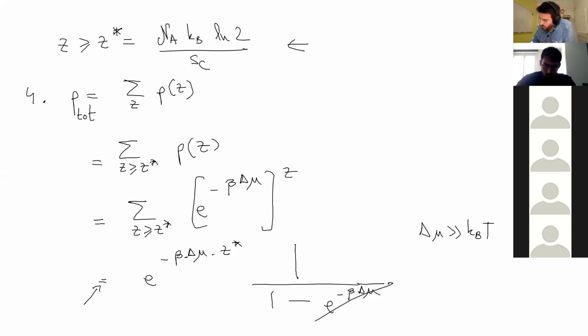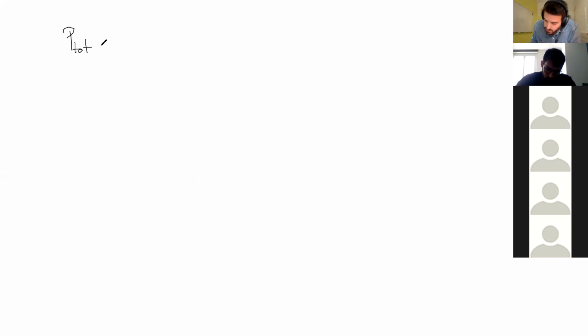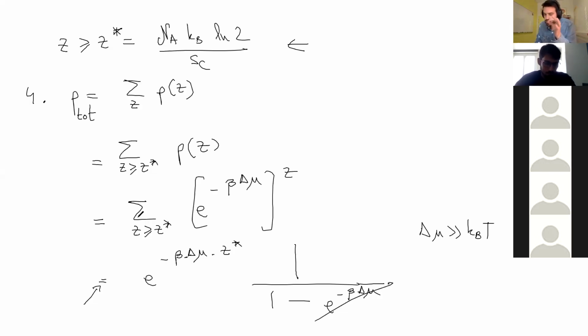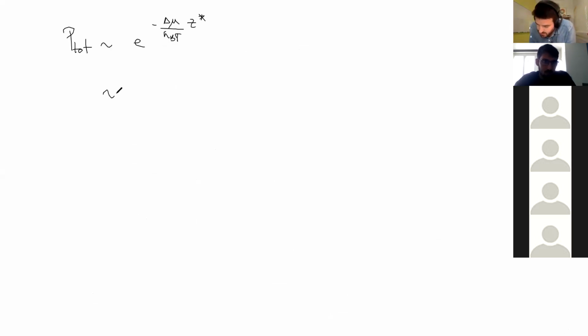And so you are left with the fact that the typical probability for relaxation is something like exp of minus delta mu over kBT, times Z star. Only Z star matters. In this series, we really don't care about the larger values. They are exponentially smaller in size, so they don't contribute, as usual with geometric series. So we are dominated by Z star, the minimum value for the size of a cluster. And so this is what we call the cooperativity. Z star is identified as the cooperativity. The minimum number of objects needed to relax is the typical number of objects needed to relax, because if you add some of them, it will exponentially be less probable.